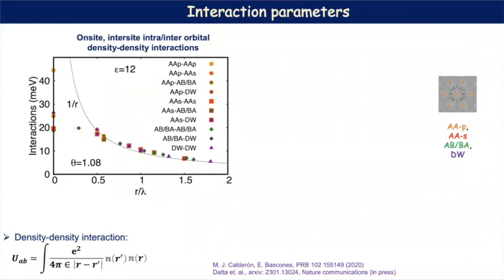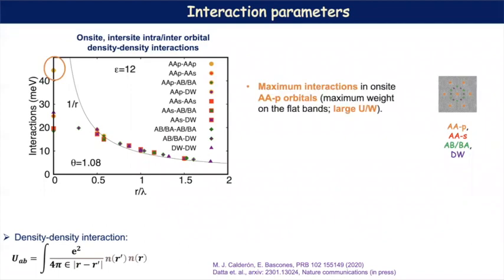So this was the single particle part, and we also calculate the interaction parameters from the Wannier functions. On the x-axis, I have the distance scaled by the Moiré length scale. What we have is basically the density-density interactions. There are many interactions because we have 8 orbitals. So there are different on-site, inter-site, and interorbital interactions, which are color-coded here in these points. But out of all these, the most important one is this one, which has the maximum value. And this one comes from the on-site interaction between these AA orbitals.